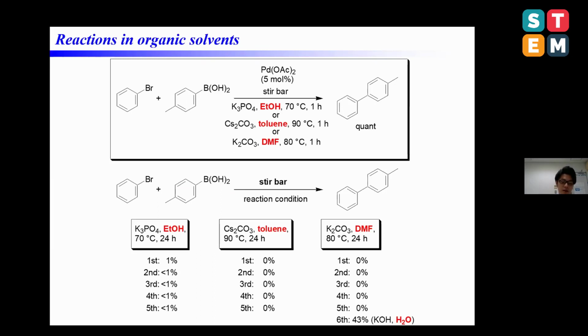Interestingly, a similar study was carried out in these organic solvents with almost no coupling product being obtained in any case. In order to confirm the existence of palladium species, when the reaction was performed using the stir bar, after the sixth run, 43% of coupling product was obtained. These results suggest that the reuse of palladium at ppm level is efficient only in the reaction in water.